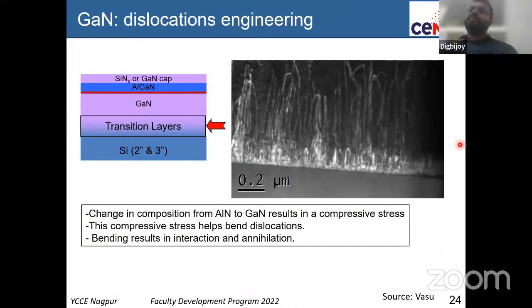So this image again is from Professor Vasu. You can see that this is a gallium nitride film, and under it is silicon. These white lines are missing lines of atoms called dislocations, and they are defects. Their density is decreasing towards the top, on which you are going to make the device. The density is worse at the bottom, where you are starting the growth.